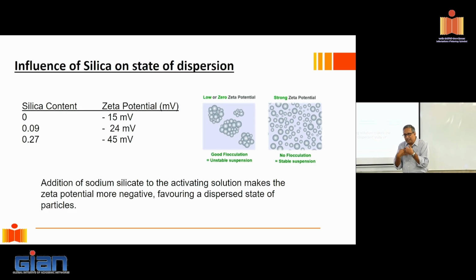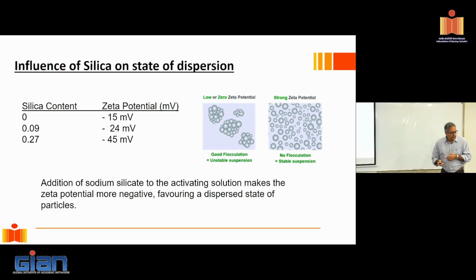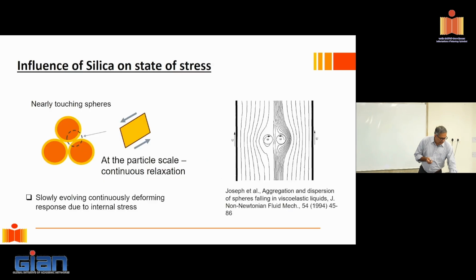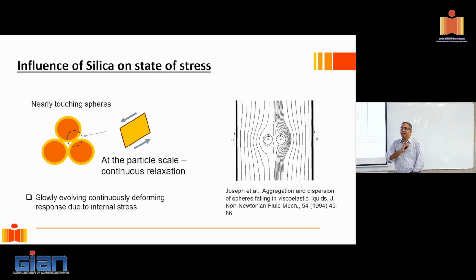That means these particles tend to separate out, and that is where I get into this problem. The issue there is that if I look at individual particles of, let's say, fly ash, and this is actually a very good approximation for fly ash, because fly ash particles, yesterday we had this discussion, are very nearly spherical, right? They get coated with this solution. Now remember, this solution is not water. This solution here is that activating solution, sodium hydroxide and sodium silicate combination.